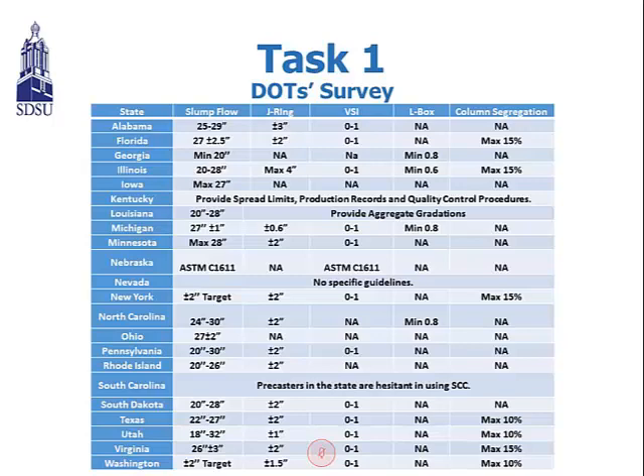And then after collecting the survey results from all the participating DOTs, we summarize them in this table, having five material characteristics, including slump flow in the first column, J-ring, VSI, the L-box, and the column segregation. For example, South Dakota allows the SCC concrete girder having slump flow ranging from 20 inches to 28 inches, and J-ring range of plus or minus 2 inches, and the VSI, which is visual stability index, of the range of 0 to 1. And they didn't account for the L-box and column segregation. You can see other DOTs' requirements for the slump flow and others.